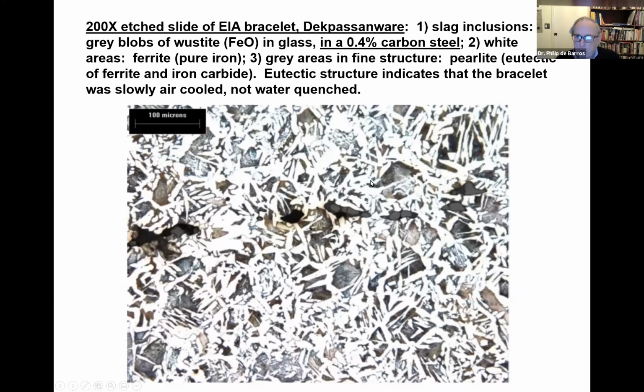And this is typical of bloomery iron, using what we call bloomery furnaces, where the iron does not melt like in a modern blast furnace, but the ore is reduced to get rid of the oxygen using carbon monoxide from the wood fuel. The bloom always has some slag mixed in it when it's produced, and it's typical of blooms to have some slag left in them.